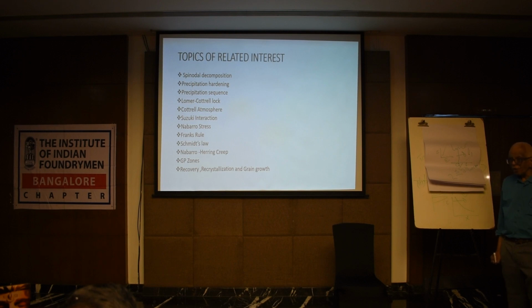That's recovery, formation of cells, subgrains in the deformed state. Recrystallization is motion of high angle grain boundaries, for example, nucleation and growth. Nuclei form near the grain boundaries. Some grains with a size advantage become the recrystallization nucleus. They grow with a high angle grain boundary, because the mobility of a high angle grain boundary is higher than the mobility of a low angle grain boundary. But that's recrystallization, as I understand it.